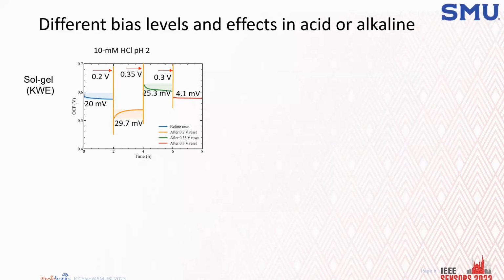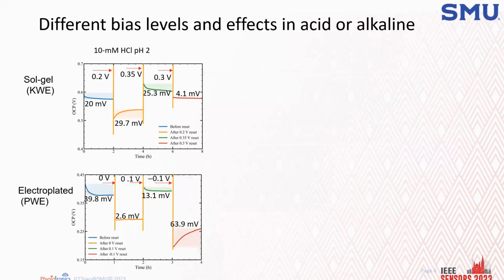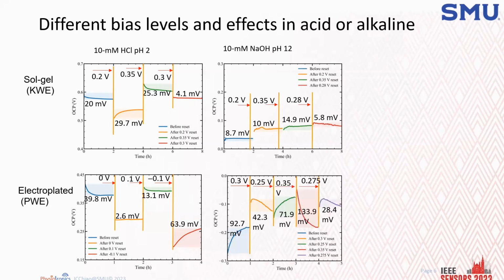So we repeat the same thing for electroplated. We found out the best reset is minus 0.1 volt. Either the best one is a 0 volt, that is only 2.6 millivolts drift. All the others either make it worse or not as good. We do find out that these phenomena are different in acids versus alkaline.